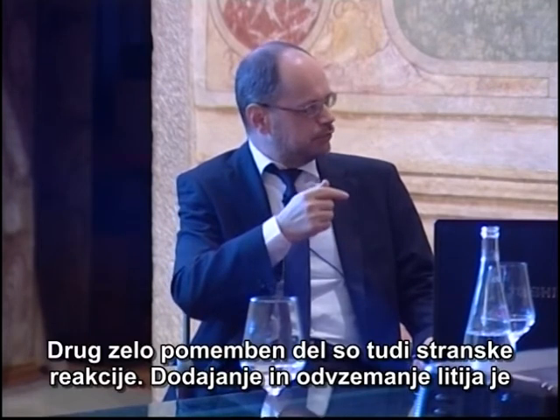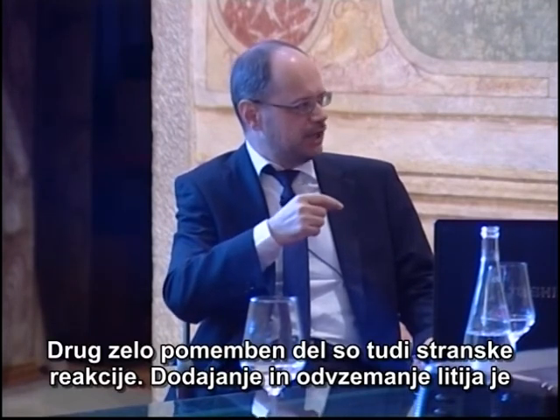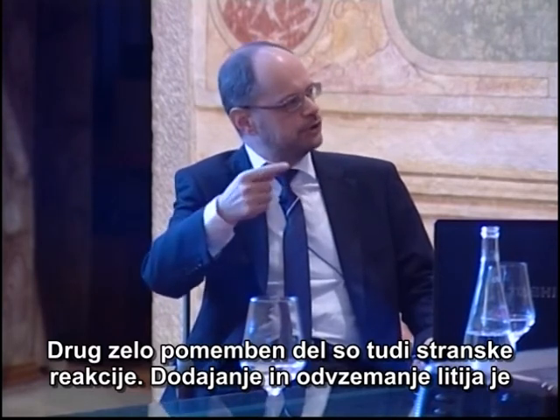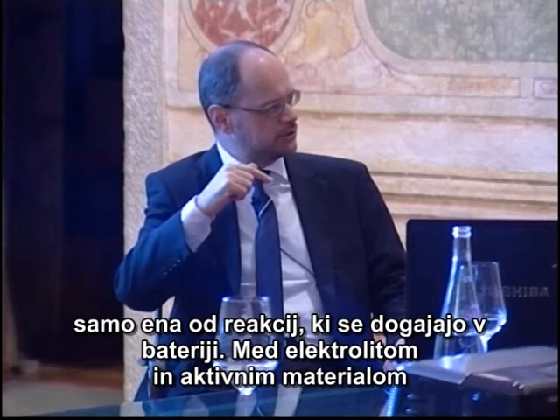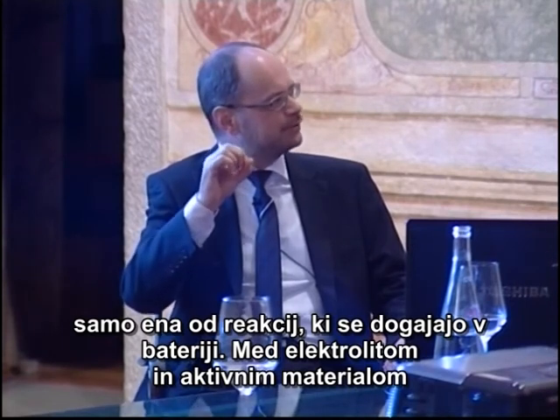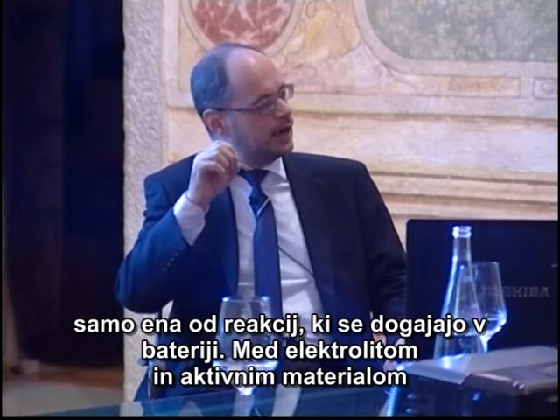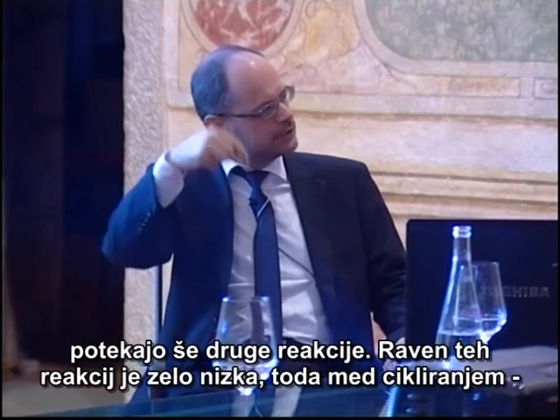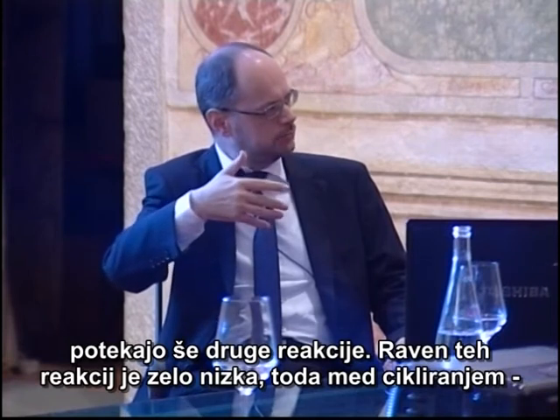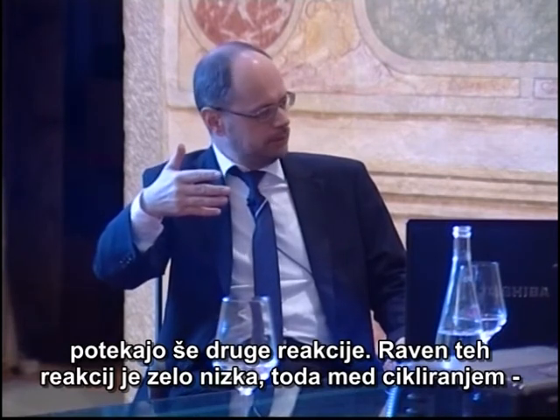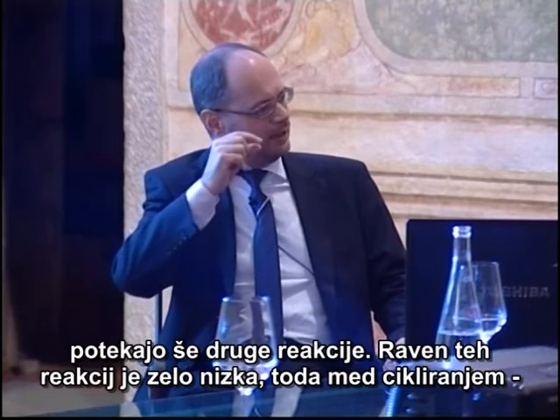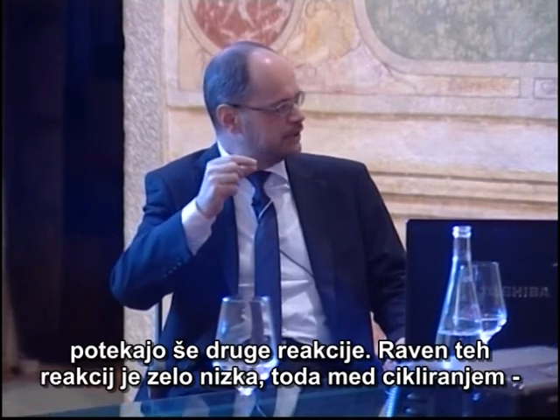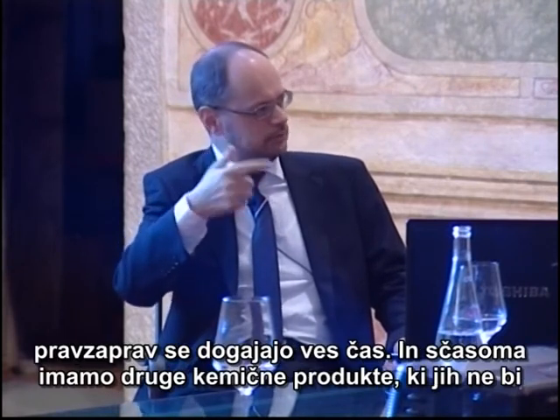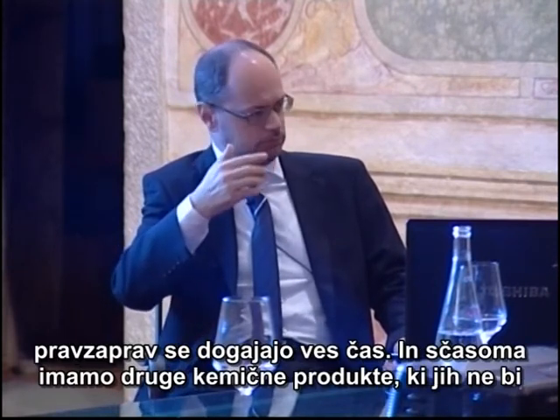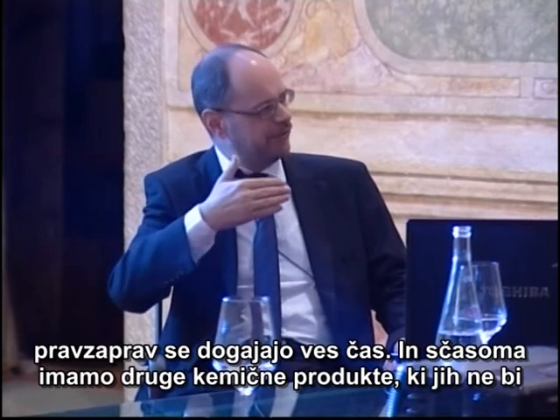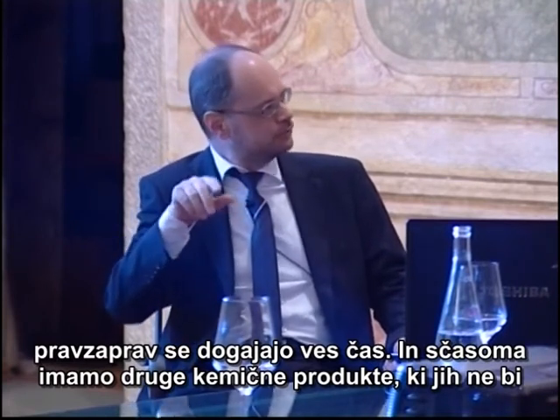Then one part which is very, very important is side reactions, because insertion of lithium inside and deinsertion outside of your material is just one chemical, or electrochemical, reaction that occurs. There are other reactions which occur between the electrolyte, where lithium ions are, and your active material. These side reactions have small rates, but during cycling they are running all the time. So over time, you have more and more other products which you don't want to have.